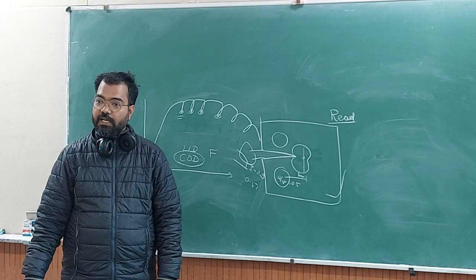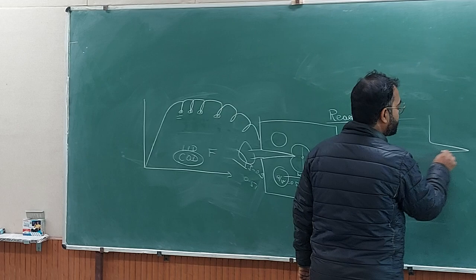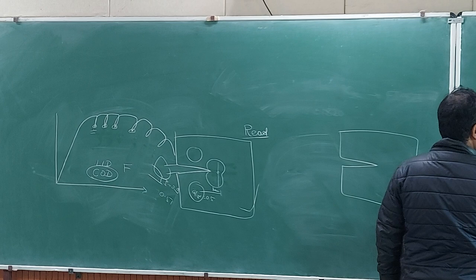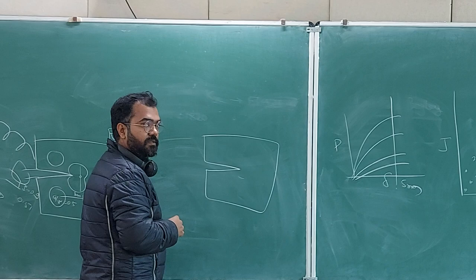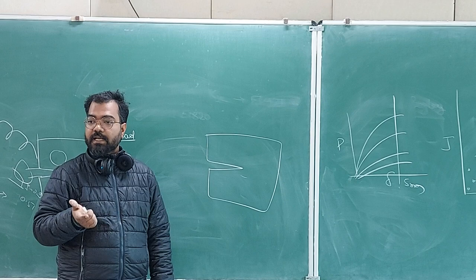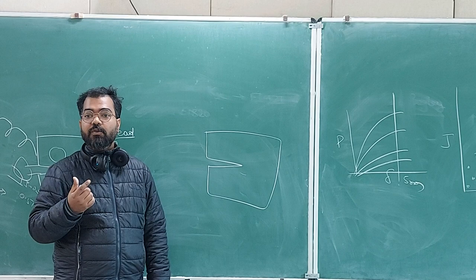Why do we break it in fatigue again? So in multi-specimen testing, I take a specimen, okay, and I have to load it to some amount of displacement value. Okay, so let us say this is 5 millimeter. So I have loaded this sample to 5 millimeter. Some deformation has happened. Okay, and if there is any crack growth or not, we are not supposed to have a crack growth in this case.